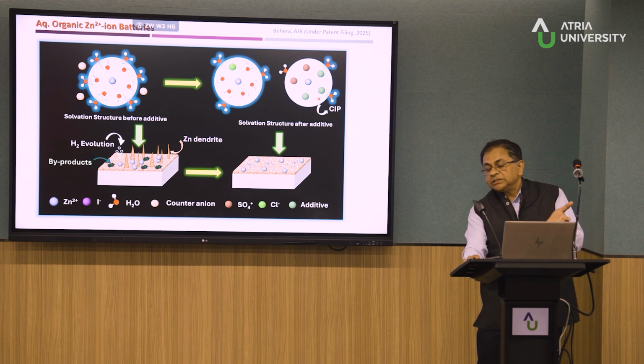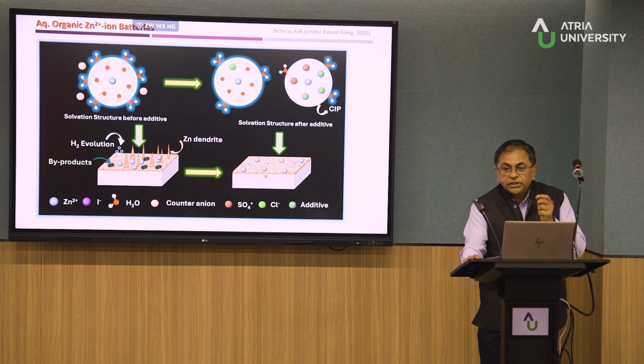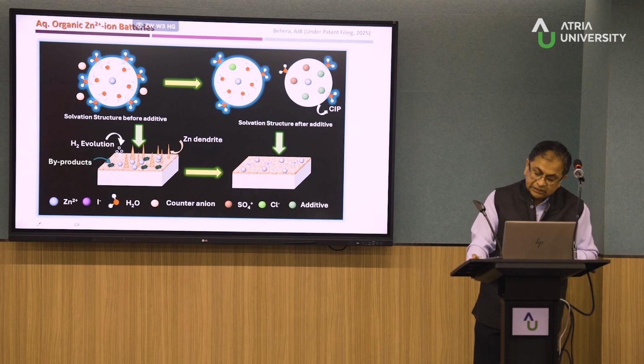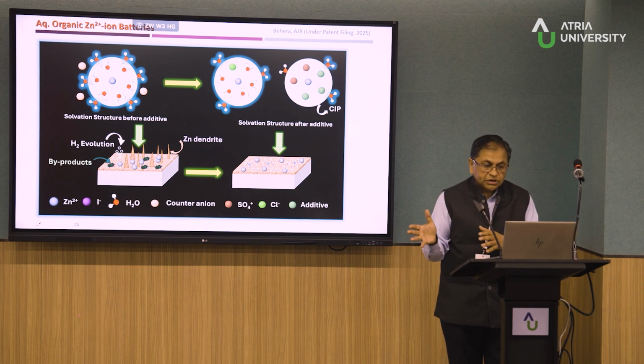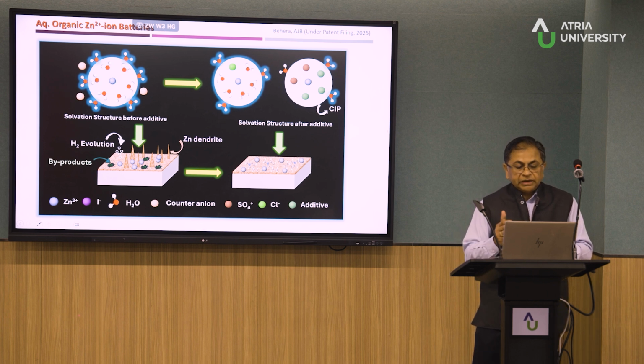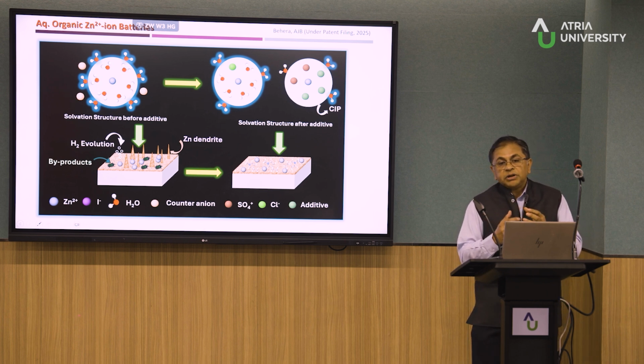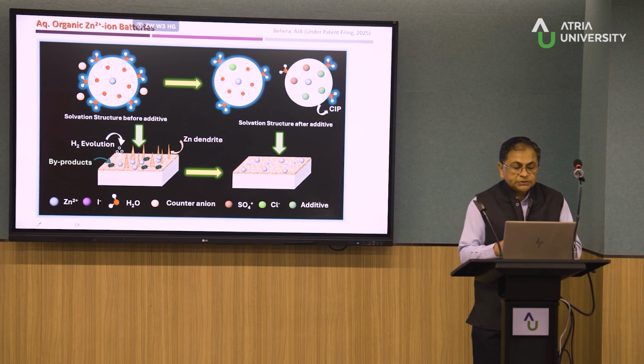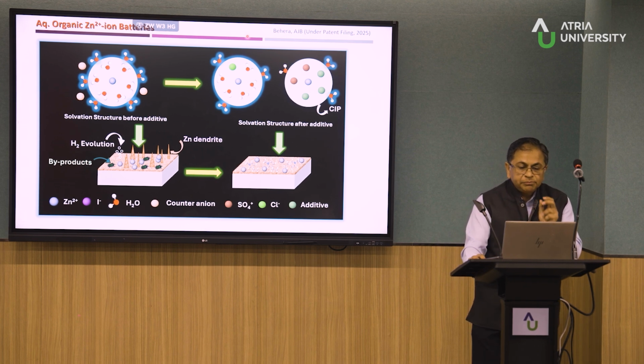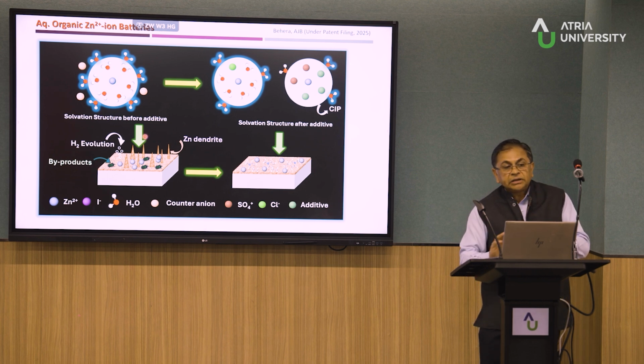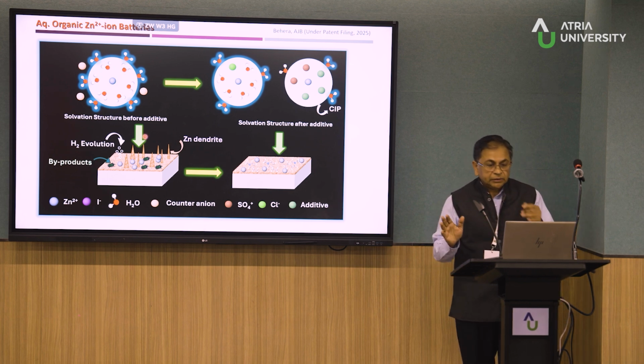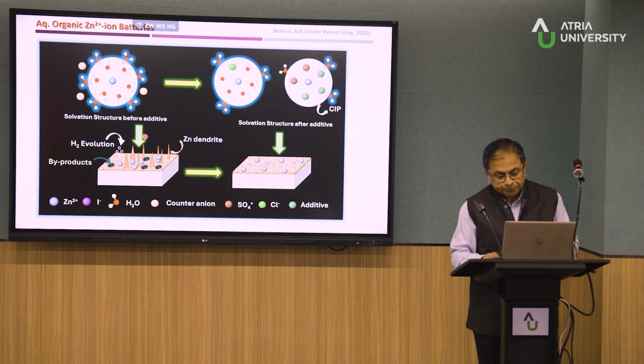So what are the advantages? The advantage is you need to get rid of the dendrites. And the important thing about all these, which is also seen in the non-aqueous counterparts, the multivalent systems, is they form a large number of these intermediate compounds. So with very simple tweaking of the electrolyte composition, you can also get rid of the byproducts. So you have a very clean system of working with a zinc ion.